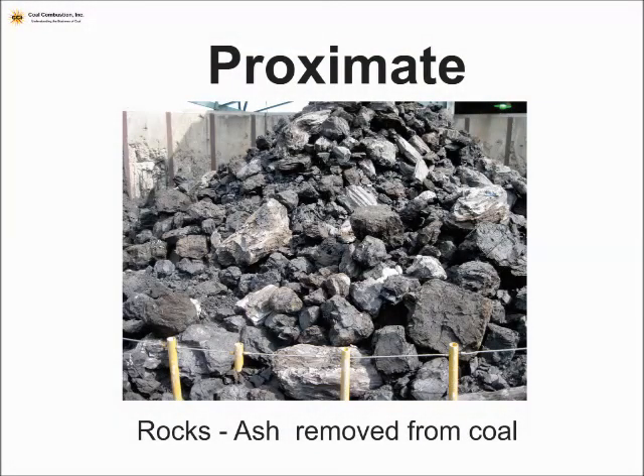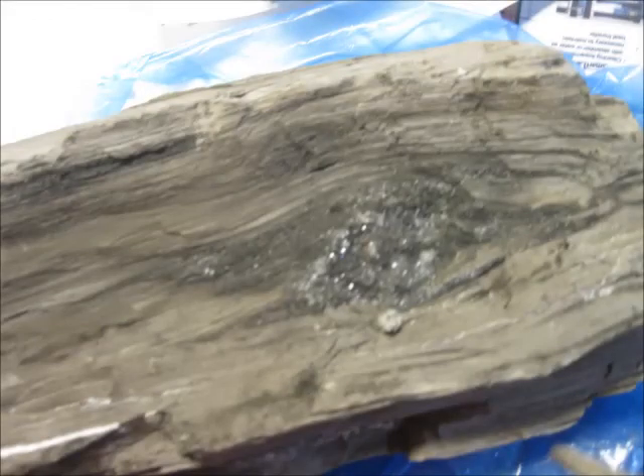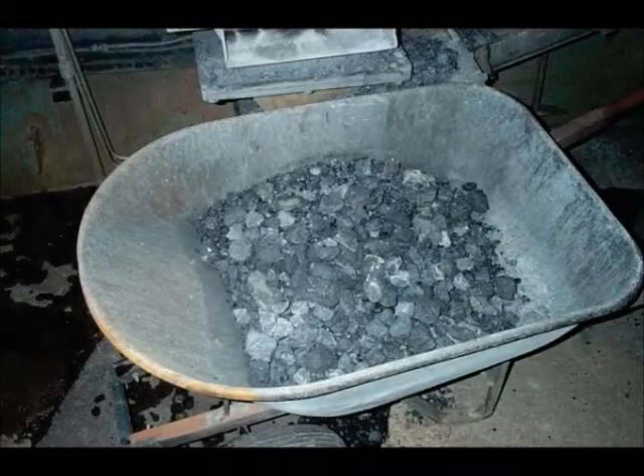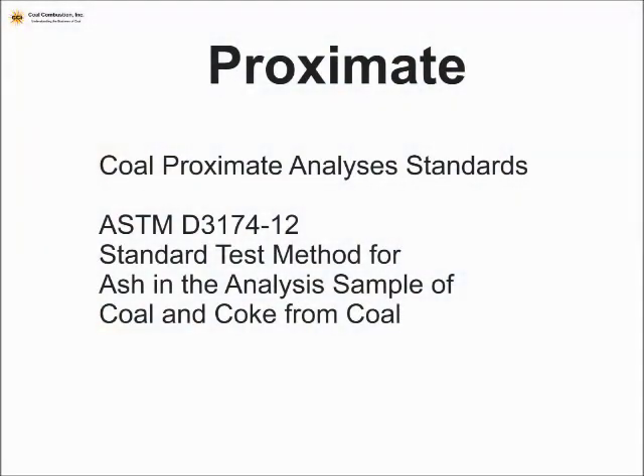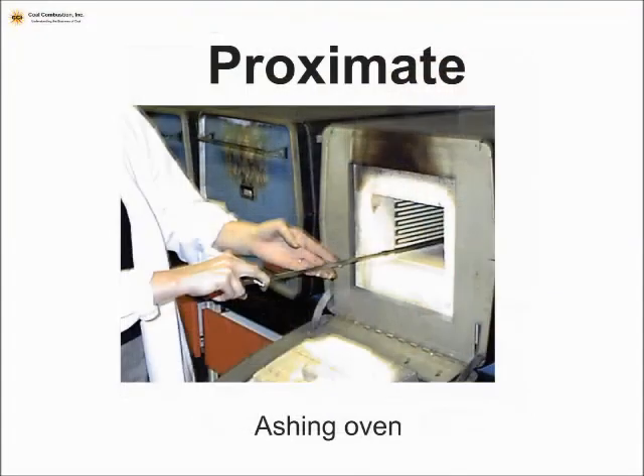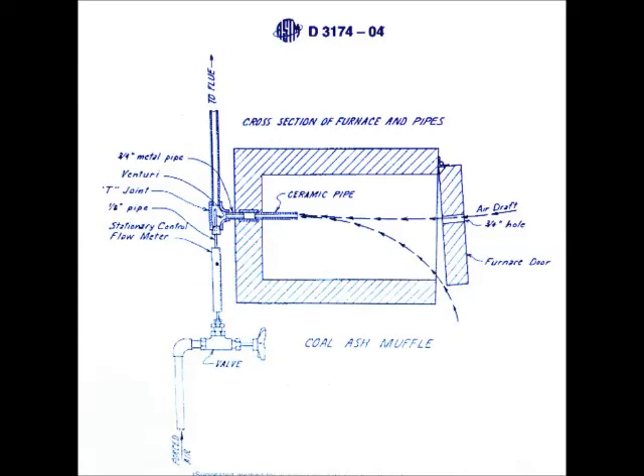The next thing is to look at the rock or ash content of the coal. There's a lot of rock and ash associated with coal, particularly if out-of-seam dilution is included. Sometimes this ash or mineral matter can include pyrites — which contain sulfur and iron — or quartz, which is a very hard abrasive material. We weigh out one gram of coal in crucibles, put it into an oven with airflow at a set temperature to burn the coal. ASTM describes how much airflow you need to ensure the coal is fully burned.